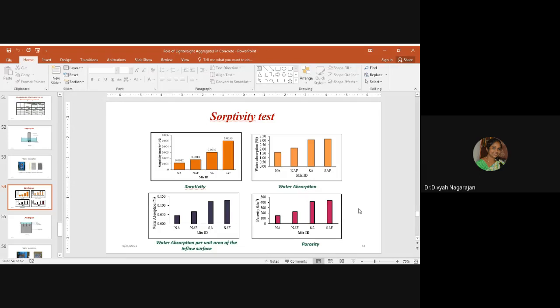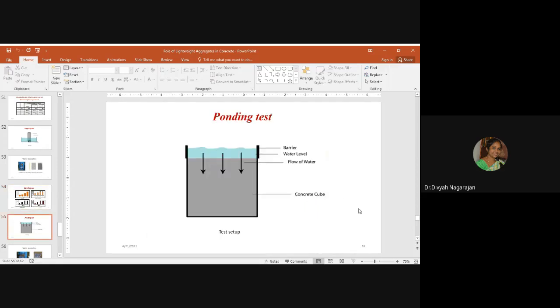Therefore, the durability test results of these values are within the acceptable range for the construction of durable concrete structures. That is, we are aiming to create a sustainable lightweight concrete that can be used in structural lightweight concreting. For better performance of these lightweight aggregates in concrete, the water absorption can also be reduced by coating these aggregates with epoxy resins. That is, pre-treatment can be done in order to reduce these effects.